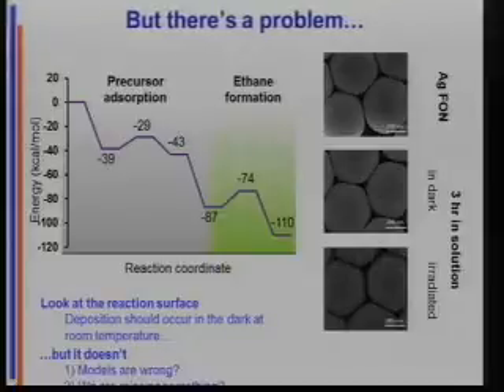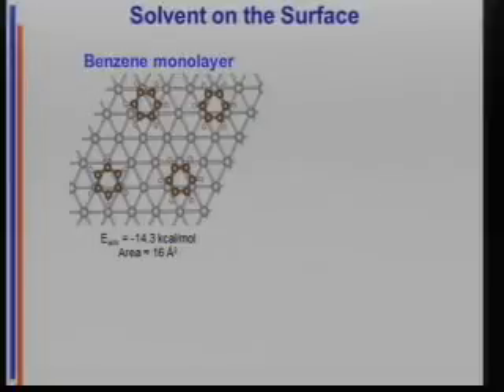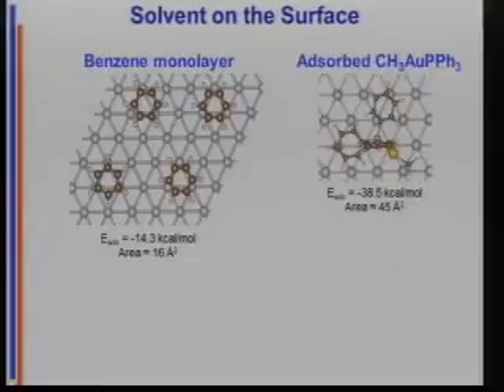And the answer is we've got a solution reaction and we did a gas phase calculation. You know, molecules coming in from the gas phase onto a naked surface. What we have in a benzene solution is a little different because we have a silver surface and benzene adsorbs onto silver, right? Okay, so now let's look at here's our surface, there's the benzene, and so each benzene is 14 kcals downhill, adsorbing, and it takes up a surface area of 16 square angstroms. Here's the precursor adsorbing. It takes up 45 square angstroms.